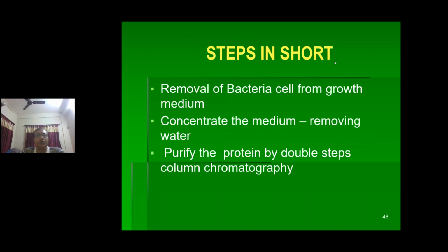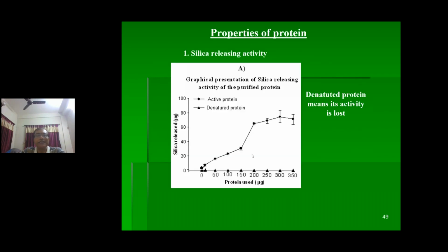The steps, in short: first we have to remove the bacterial cells from the growth medium, then concentrate the medium, removing the water. Then we purify the protein by double-step column chromatography. And if we see the silica-releasing activity of this protein, this curve is your active protein, and this x-axis is the denatured protein. Denatured protein means the silica-releasing activity of that protein has been lost. How is it lost? Normally it is done by heating. We can lose the activity of this protein. So we check that if we add the active protein, it has silica-leaching capacity, but if we denature the protein, it has no silica-releasing effect.